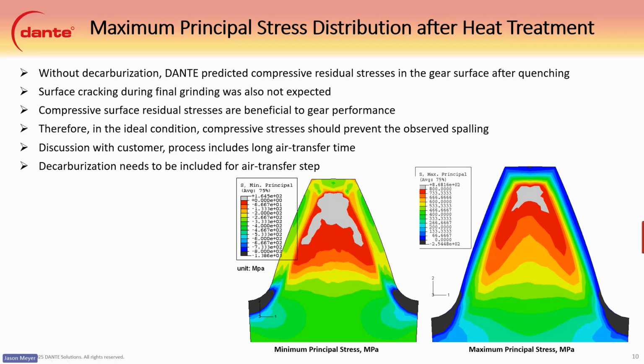transformation to martensite from austenite happens at the case core interface first and then works its way to the surface. It kind of goes from the inside out almost. And what happens is that those volume expansions keep adding up until you get to the surface, and it pulls the surface into compression from the last transformation there. So in the ideal condition, compressive stresses should prevent the observed spalling.